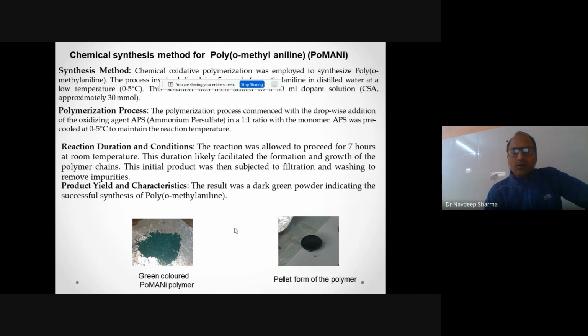After the filtering process, the material is dried in a vacuum oven to remove the moisture from the conducting polymer. The process takes a long time, 24 hours in the vacuum oven. After that, we obtained a green colored poly(ortho-methyl aniline) polymer, shown in the figure, which gives the first indication that our conducting polymer is prepared.